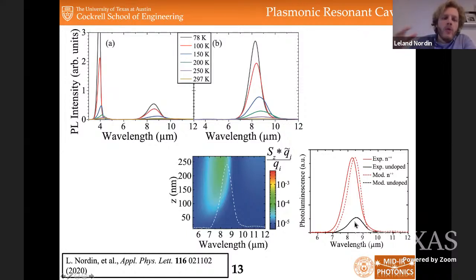And then for the actual implications for optoelectronic active regions, it seems as though we can grow high quality crystal on top of plasmonic materials, and we don't see any degradation in quality, which in the near IR visible world, people have struggled a little bit more to do, especially with some of the embedded nanoparticle work. So we can grow these type 2 superlattices on top of plasmonic materials. What can we then do as far as actually enhancing optoelectronics? That is sort of the name of the talk.